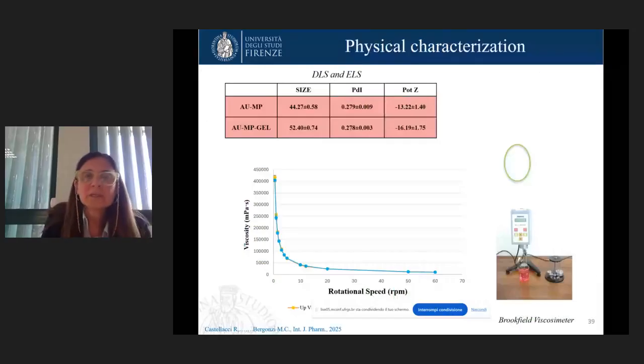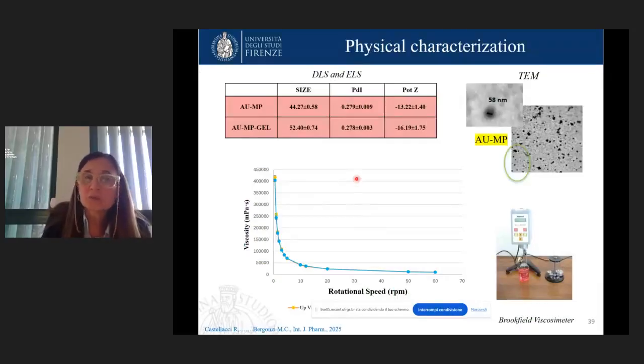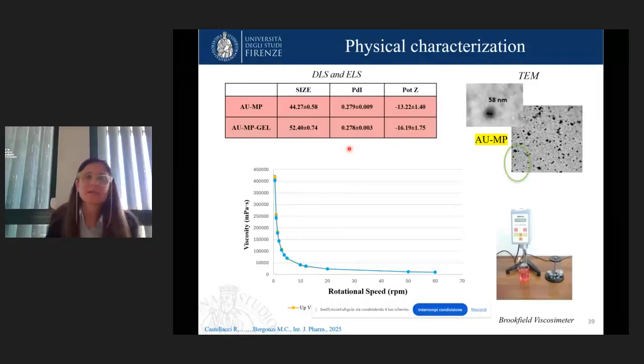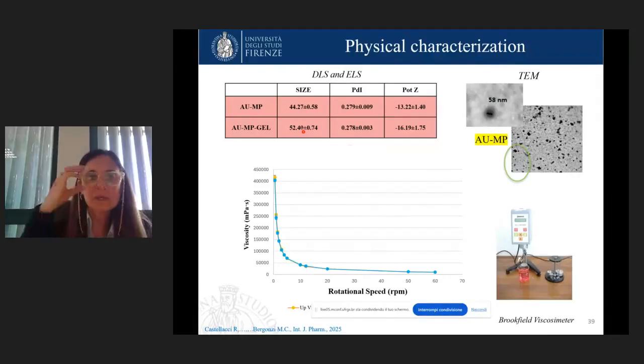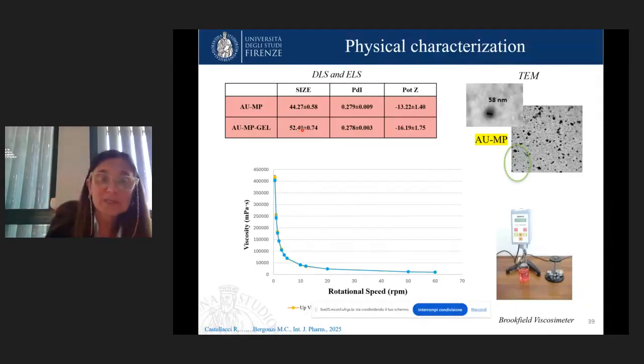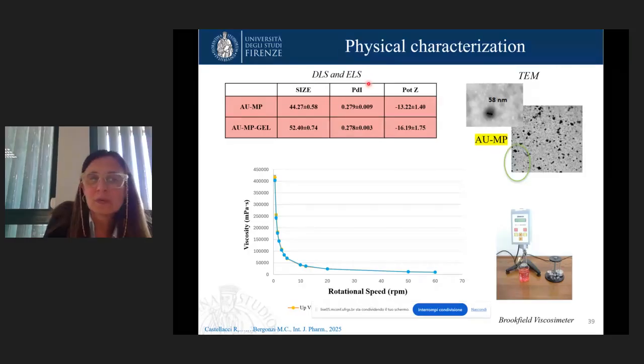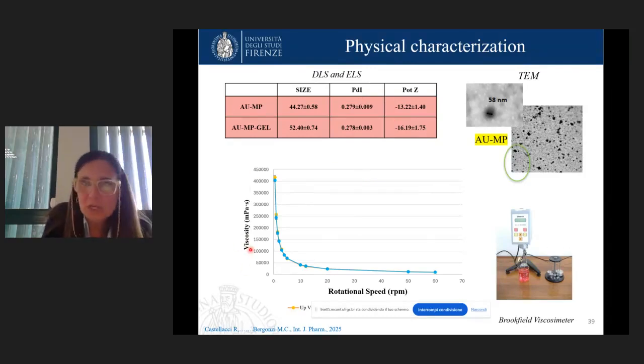We characterize the micelles and also the gel using the light scattering technique. We obtain a very small size of micelles inside the gel, a good system with very good homogeneity and high zeta potential, but we also characterize the viscosity. Then, from the rheological point of view, related to the viscosity of the gel, the system